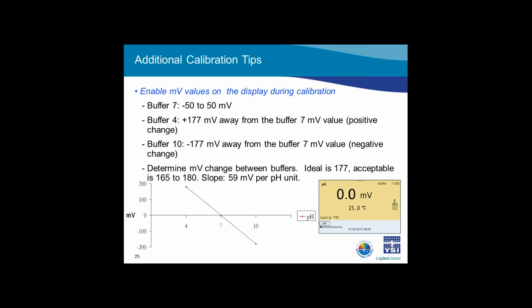The acceptable values for the millivolt signal in buffer 7 is between -50 and +50. This is a general rule for all pH electrodes. Lab-specific electrodes or specialty electrodes may have a tighter recommended range for this, like the YSI TrueLine, ScienceLine, and IOLine electrodes, which have a millivolt range of -30 to +30 when in buffer 7. The acceptable millivolt values for the other buffers depends on what the millivolt value is in the 7, because we are looking to establish a slope.